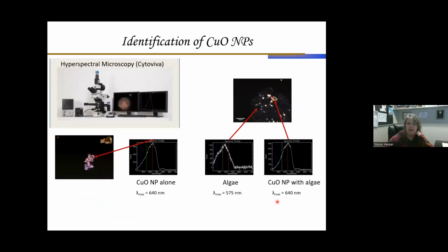To identify the copper oxide nanoparticles, we have a Cytoviva system for hyperspectral imaging analysis, where you can basically take a scan in dark field microscopy, and the metal nanoparticles in particular are really, really bright and distinctive. And so we can train the library to identify the copper nanoparticles. So this is an example of copper alone. We have the copper oxide mixed with the algae. You can see if you probe the area with the algae, it gives you a very different signature than with the copper nanoparticles, and you can see them visually.